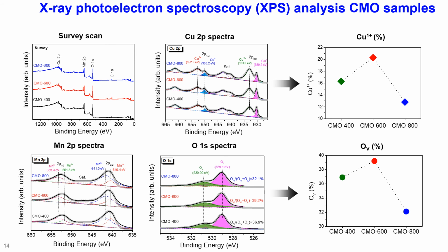X-ray photoelectron spectroscopy, that is XPS analysis of CMO samples, has been shown here. It confirms the formation of CMO and their oxidation states. Here we could clearly see that CMO 600 possessed the high number of Cu1+ percentage and the corresponding oxygen vacancy percentage.